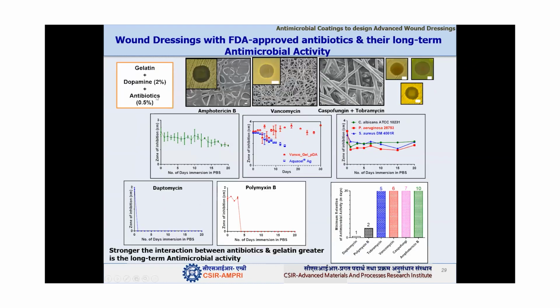Then after that, what we did: now this is the combination of the crosslinker and the base material. The third component, as I have mentioned, is the antimicrobial component. In the first study, we actually added antibiotics only. We have done different kinds of antibiotics like amphotericin B, vancomycin, then the combination of antifungal drug caspofungin and tobramycin. Tobramycin is a broad-spectrum antibacterial drug. We have used different combinations of drugs in the fibers, and you can see their morphology and this diffusion result.